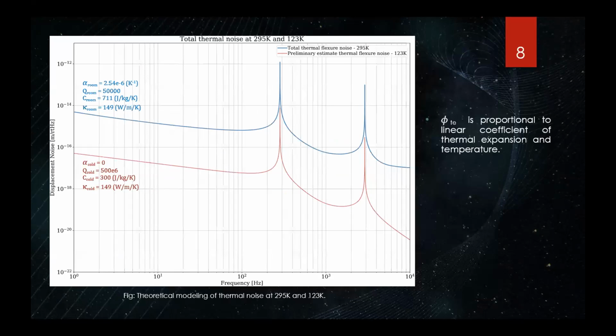So if we were now to cool this flexure, and if you look at these parameters on your left-hand side, what changes roughly between going from room temperature to cryogenic, you can see that your trace drops down by almost 2 orders of magnitude. And now what you're trying to measure, the off-resonance measurement, lies at the level of roughly 10^-17 meters per root hertz. And like I mentioned, the thermoelastic loss is proportional to the linear coefficient of thermal expansion and temperature. So as those change, you can see that your total thermal noise has dropped down significantly.